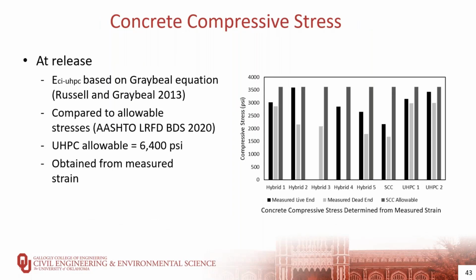So here the figure on the right shows the compressive stresses determined from the measured strain at both ends of the pre-stressed girders and the SCC allowable stress based on AASHTO LRFD at release. At each UHPC end, the measured stress was calculated using the measured strain from the vibrating wire strain gauge and the modulus of elasticity of UHPC that was proposed by Russell and Graybeal. Similarly, the measured stress at each end of the SCC was obtained from the measured strain and modulus of elasticity determined by AASHTO LRFD. All the measured stresses were within the stress limit determined by the SCC.